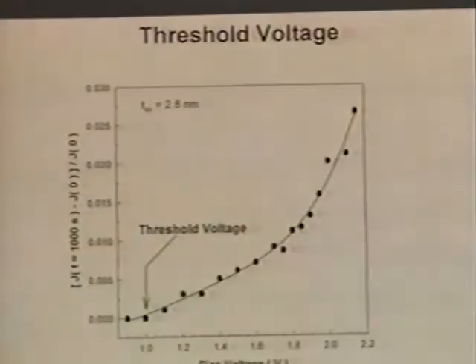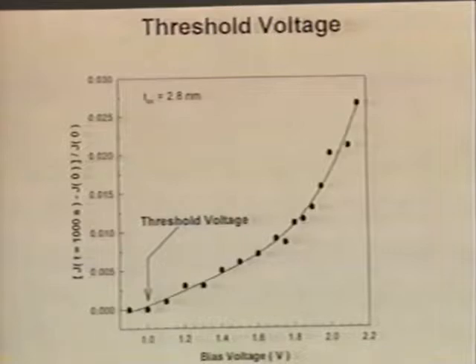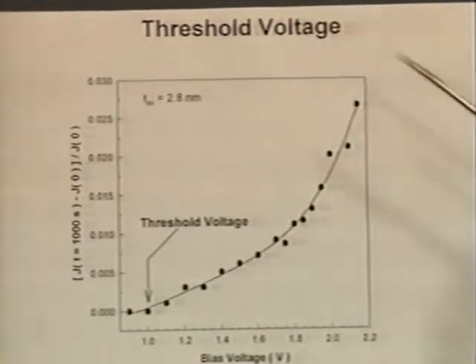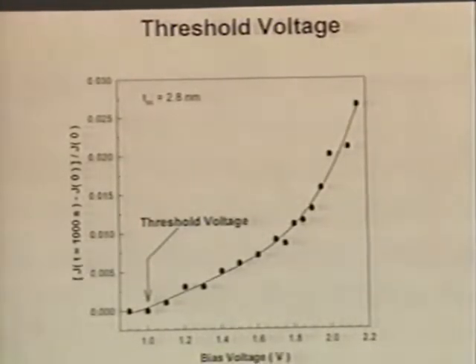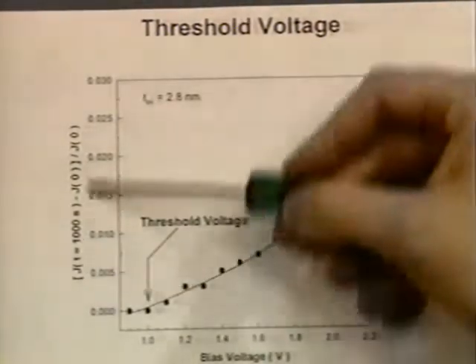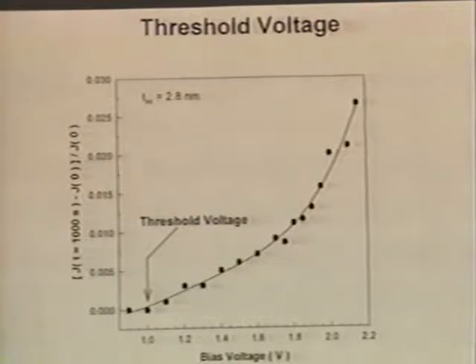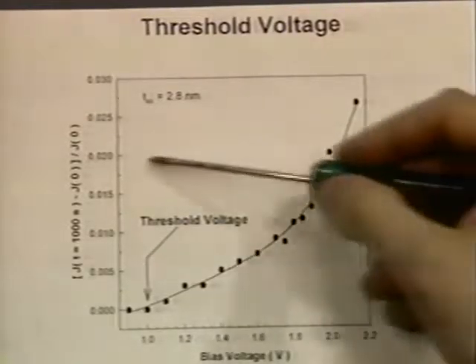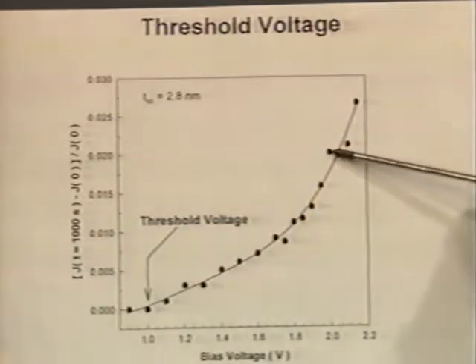I want to talk now about sort of the characteristics of this defect creation or direct tunneling degradation. I want to show some properties of the effect. For example, there's a threshold voltage for the turning on of this effect. I'm plotting the fractional change in the current measured at a particular time, 1,000 seconds, versus the bias voltage that we sit at. The previous foil I showed you, we were sitting at 2 volts across the device. So that would be right here, sit at 2 volts, and after 1,000 seconds, there's 2.0–2.5% change in the current.